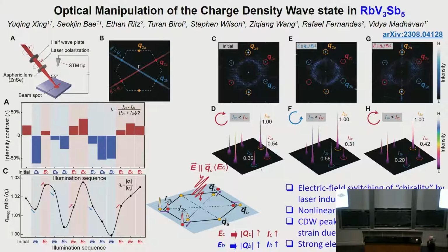All right? So that is great progress. At least we know what is really changing. It is indeed the lattice becoming chiral, if you wish. The chirality is a reflection of the lattice strain. So it's strong electron-phonon coupling, or zone boundary phonon coupling, that leads to this. This doesn't say anything about time reversal symmetry breaking. So we thought we just need to apply the field and see if we can switch the chirality together with the lattice strain. If that's the case, then we have really gained insight into this.